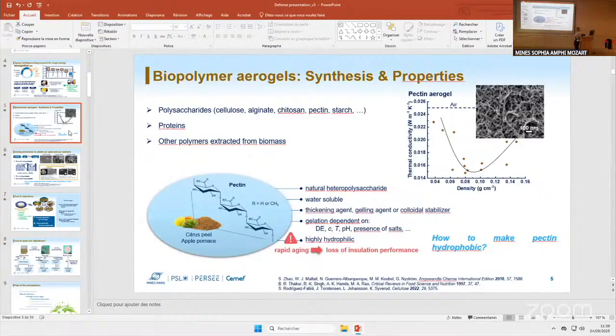How would this be different in your materials, or would this also be like when you physically compress two nanofibril fiber structures together? How is this different than a chemically made structure, let's say, during the coagulation and grafting? So usually when we use more matter in our materials, we don't get reduced pore size after the end of the process. So we don't really get higher specific surface area. The matter does not contribute directly like this.